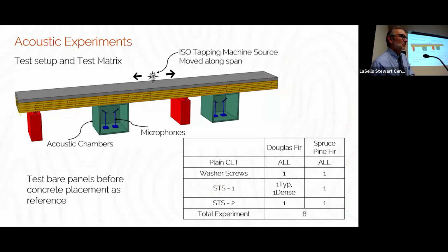All right, the other two parts of this, which we're just starting to undertake, are looking at the acoustic performance. Here we're looking at relative acoustic performance, not absolute acoustic performance. So we have, again, two different species, Doug fir and SPF. We've got three different types of fasteners. We've got one single concrete, 2.5 inches thick. Now what we're going to do is use an ISO tapping machine on top to look at the sound transmission through the composite. But we want to know the relative performance, so we're going to do all the ISO tapping of each individual CLT slab before we add the concrete, so we can tell you how it changes with the concrete addition. We've got microphones underneath as a receiving room to determine what the sound pressures are underneath.